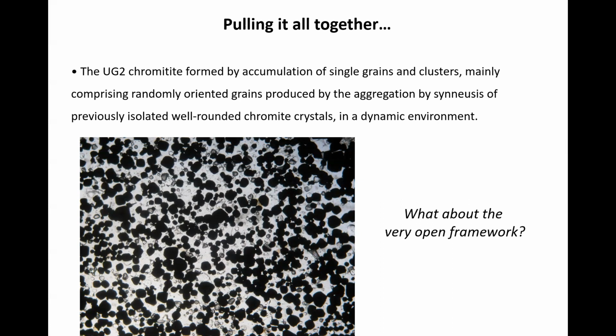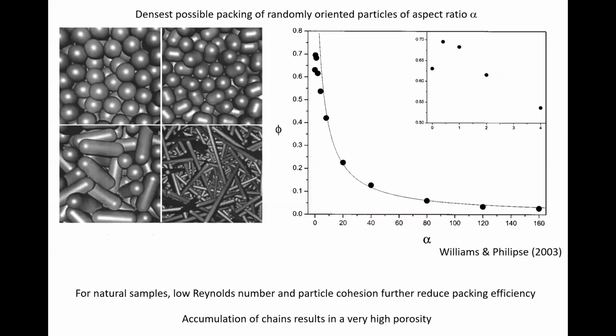But then you need to think, hang on a second, we're not dropping down single round grains, we're dropping down clusters and chains. And the packing efficiency of things with an aspect ratio that's not 1 is very, very sensitive to shape. So this is some beautiful work by Williams and Philipse from 20 years ago now, where they did random close packing using a computer.